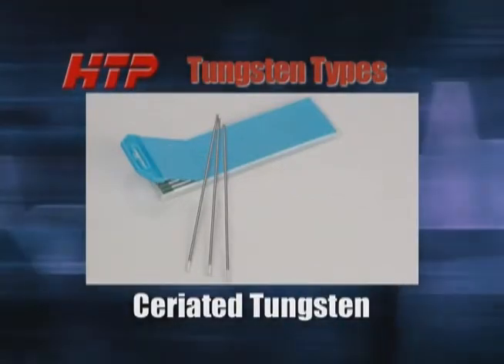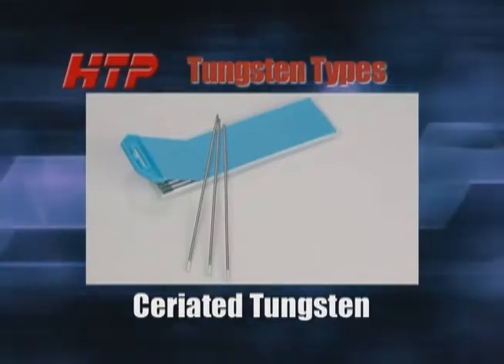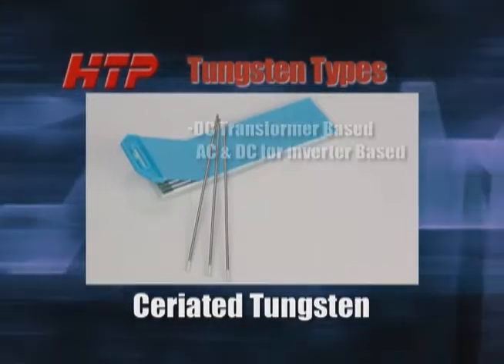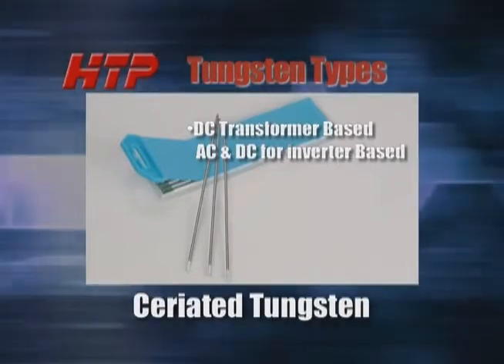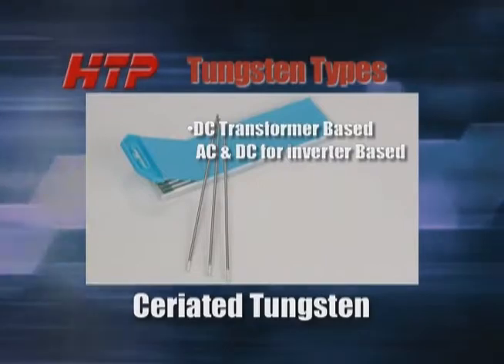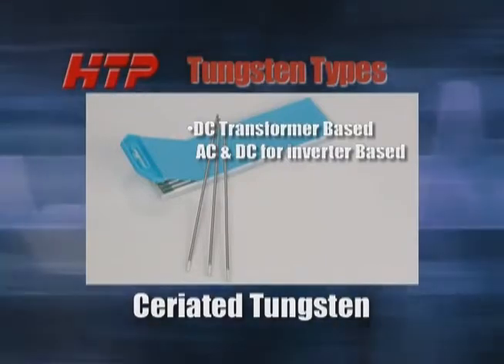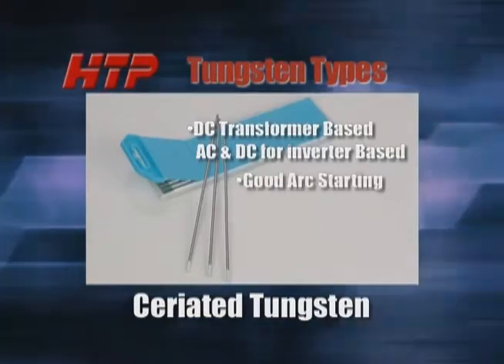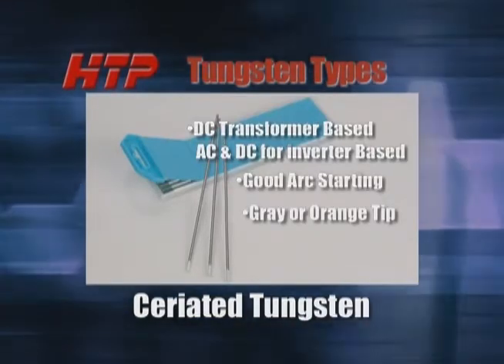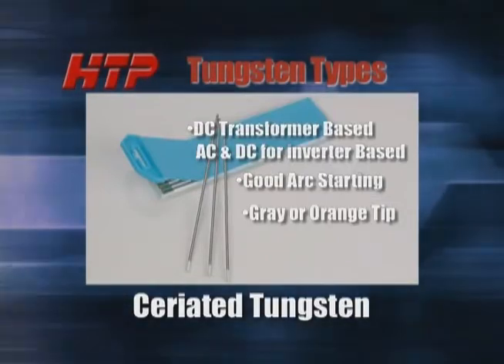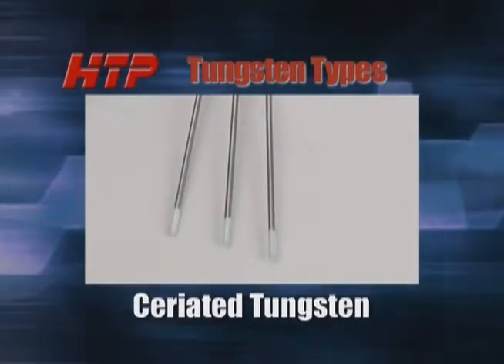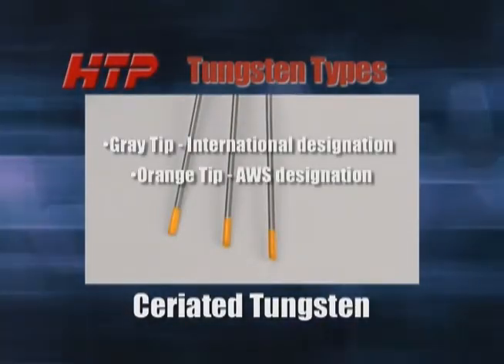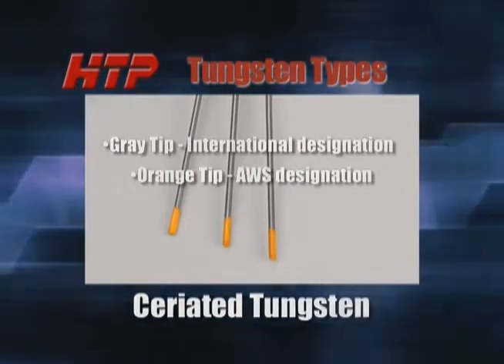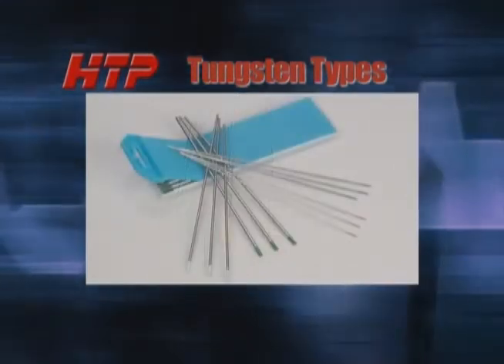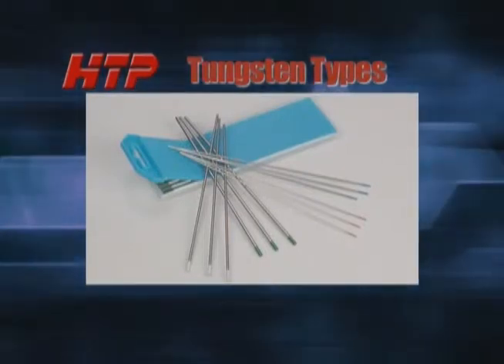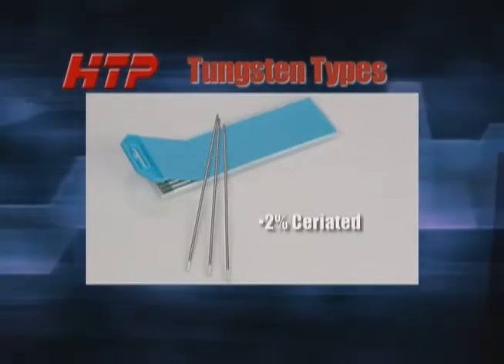2% ceriated tungsten is an excellent substitute for thoriated tungsten to eliminate the radiation hazard. It is generally used in the DC mode for welding steel and stainless steel on transformer-based machines and can be used for both AC and DC welding with inverter-based machines. It has a low erosion rate and gives you excellent arc starts with good arc stability. Designated by a gray tip or an orange tip for 2% ceriated. Why 2 colors? Gray is the international designation and orange is the AWS designation. For some reason they deviate on this type of tungsten. Since the InverTIG 201 is an inverter-based machine, we will be using 2% ceriated tungsten exclusively in this video.